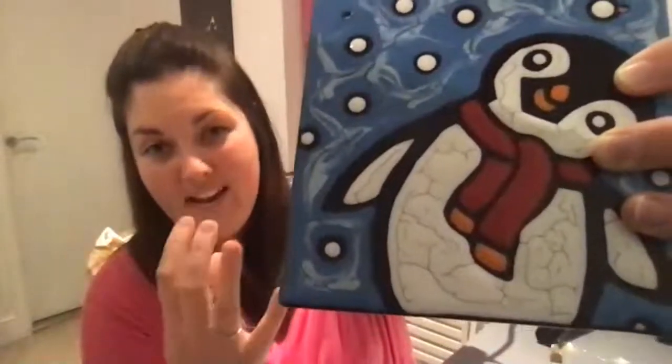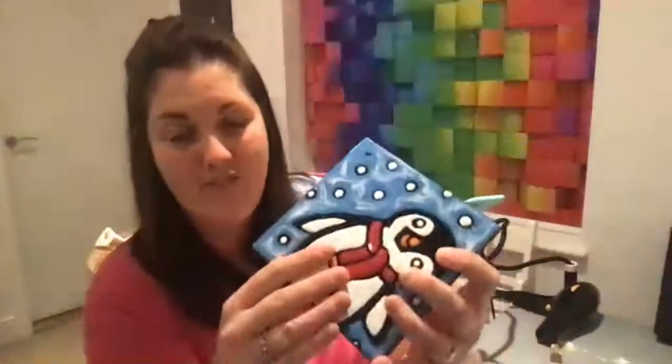So it's called crawling, and it kind of moves where it's not supposed to. But because we rapid dry these and we cause the glaze to crack in these lovely little bits here, there's all these beautiful cracks coming in. They're not actually a full crack. If you imagine a dry riverbed, it's that kind of thing. It's where it's dried out and it's moved, but it almost gives it enough space that it then doesn't crawl off the piece when it's fired.